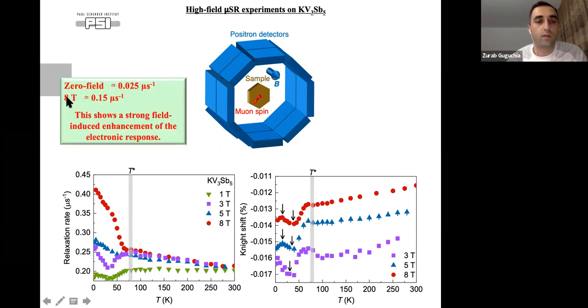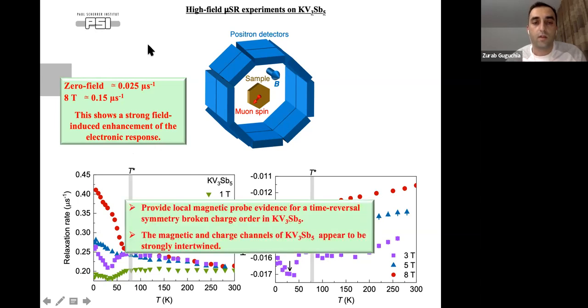So compared to zero field, in 8 Tesla we have an increase of relaxation by 0.15 inverse microsecond, which shows that there is a strong field-induced enhancement of the electronic response, and it's very clear. So with these muon measurements, we provided local magnetic probe evidence for this time reversal symmetry broken charge order in this compound. And this means that the magnetic and charge channels appear to be strongly intertwined in this kagome